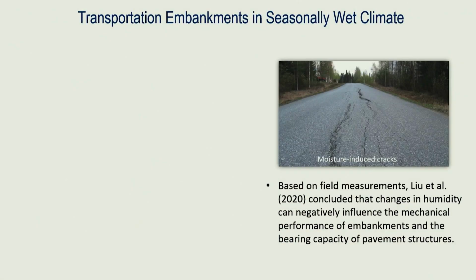So one of the questions that may arise would be, what's wrong with having a little bit of moisture in embankments? Is that dangerous? Is that not good for the embankment? Well, research, this was a published paper in 2020, and people conducted research to try to identify what happened with the change in humidity inside transportation embankment, and how does that affect the overall mechanical performance of the system. And what has been revealed in this study is that change in humidity can definitely influence the mechanical performance of embankment, as well as the bearing capacity of the pavement structure.